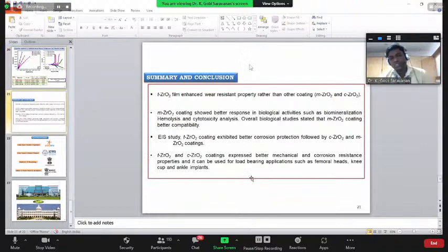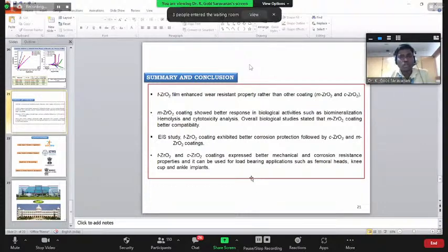So with this, we concluded that for mechanical property and corrosion resistant property, tetragonal zirconia is the best material we have found. For biological applications like protein absorption, platelets, cytotoxic behavior and biomineralization, monoclinic zirconia has shown to be the best material. So for load bearing applications, tetragonal zirconia will be best. For other than load bearing implants, we can refer to the monoclinic as well as cubic material.